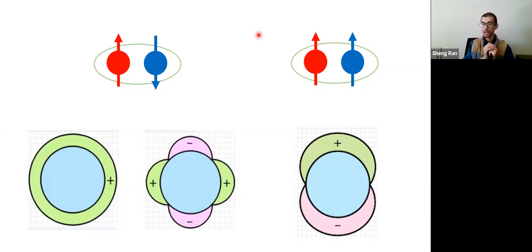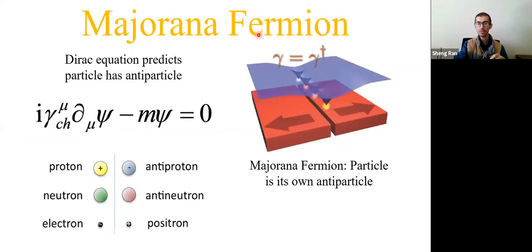Now, it turns out this spin parallel or triplet spin superconductor is a very rare quantum phenomenon. So far, we discovered about 10,000 superconducting compounds. That includes all the dopings for iron pnictide and the cuprates. But within these 10,000 compounds, there are probably less than 5 that are really candidates for a spin triplet pair. It's a very rare quantum phenomenon. But recently, in the past 10, 20 years, it started to get more and more attention. The reason is related to the so-called Majorana fermions.